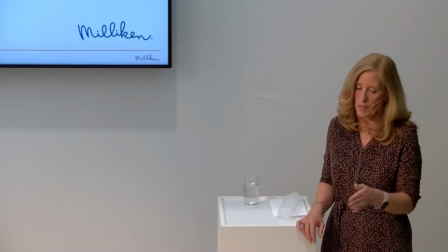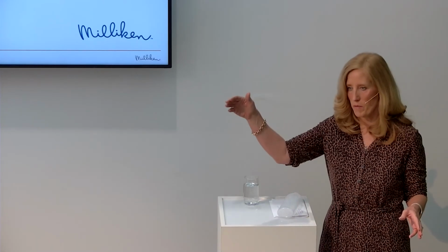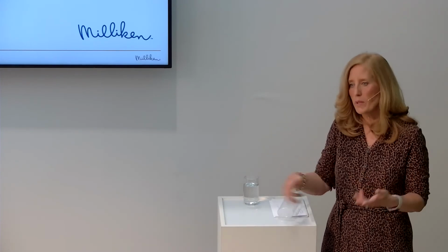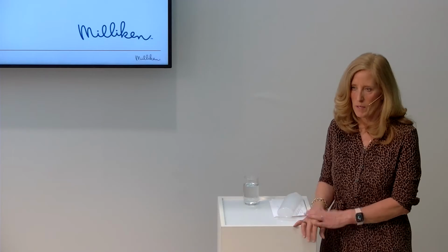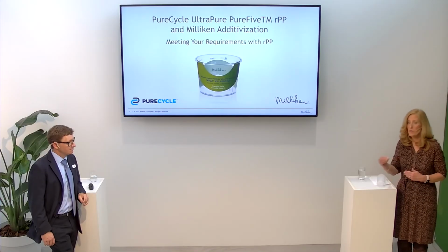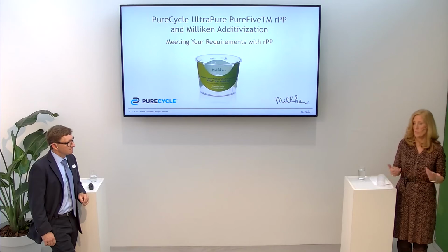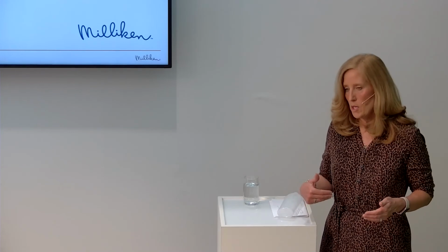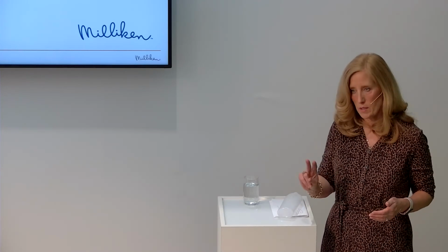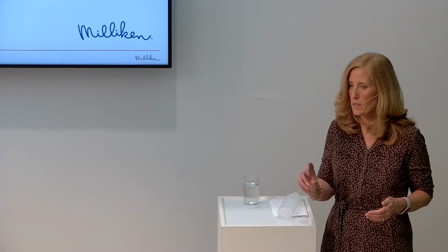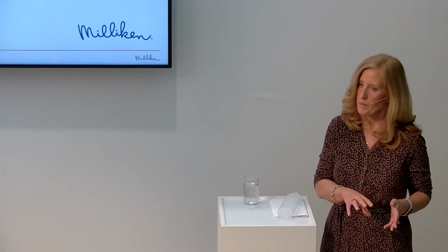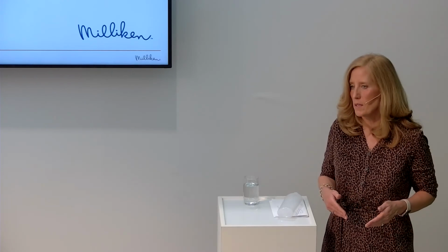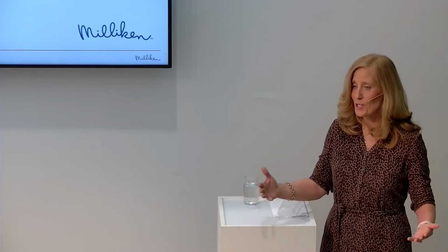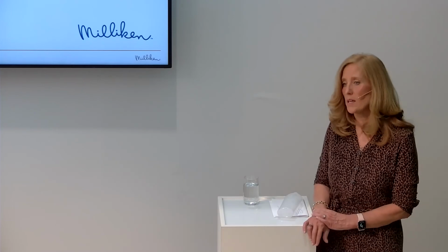The raffia material that we get in can be a 0.35, but it can also be a 16 or a 20 melt flow. And again, we find when we get the raffia in and we're blending it all the time, hitting that 15 melt is really easy right now. Ultimately, we hope for sorting in the future, if we need to, for melt flow, for critical mass, for someone who wants to pay me extra money. Our sort lines are infrared to start out with, IR scanning systems, and then robotics. We invested in the robotics for two reasons: if we need to take a certain format and sort it out because of the melt flow, or if we need to target food grade. So we have those two things in our pre-processing. I want to have the broadest conditions of use with the broadest supply, but I've planned for the worst case scenario to be able to still answer the needs of the customers.